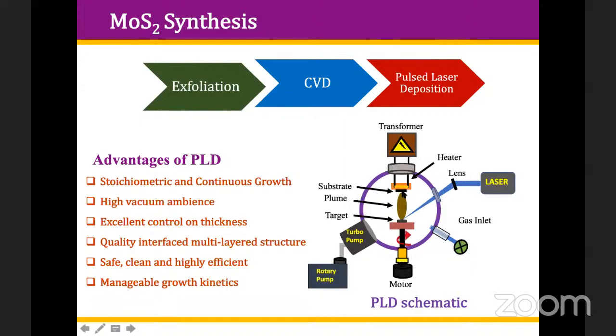Why? Because PLD gives stoichiometric and continuous growth of deposition. It needs a high vacuum ambience, so the possibility of defects in the system is very, very low. And there is excellent control on the thickness of this material. By changing the number of pulses, you can make a monolayer, bilayer, trilayer, or control the thickness very precisely. If you can control the thickness, the interface can also be made very sharp and efficient. This is a very safe, clean, and highly efficient technology, with manageable growth kinetics.